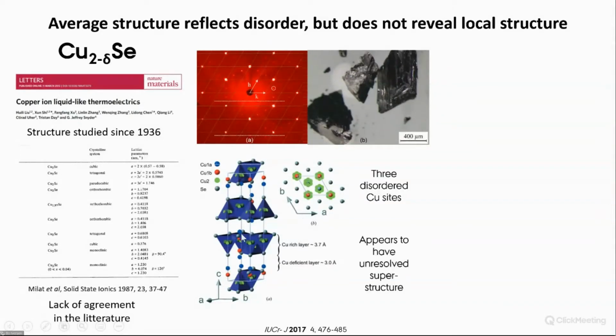So you see, you have a copper-rich layer and a copper-deficient layer. And then on each of the copper sites, you have multiple occupancies. But it was also clear from these data, if you look up here with the circle, that there were extra Bragg spots, or what looked like Bragg spots, that were not indexed by the unit cell. So it looked like it had a superstructure.